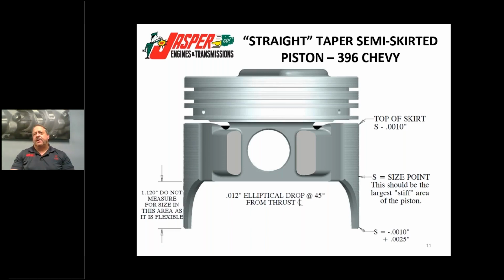This is why we put so much into it, because if you look at this short compression height, when things start getting to about an inch to 1.1 inch at an OE level on a piston, then you've got a barrel profile to it, and you're going to run it 1.5 thousandths or 2 thousandths. That could rock pretty easily if you don't have the correct profile. So that's why I'm really particular on running the late model engines and getting these profiles correct. If you do that rainbow shape, as I noted before, that stops the rock.